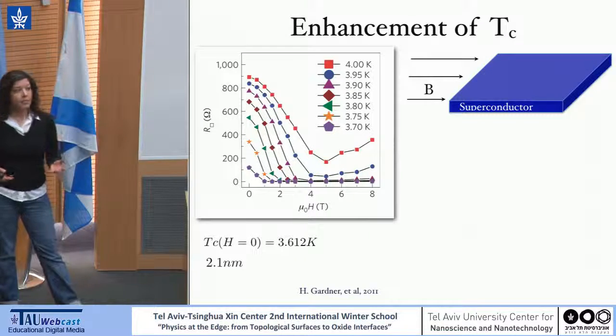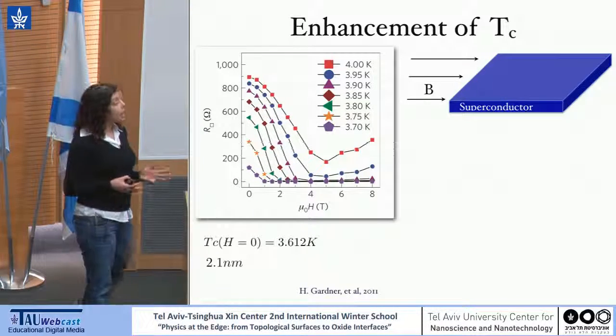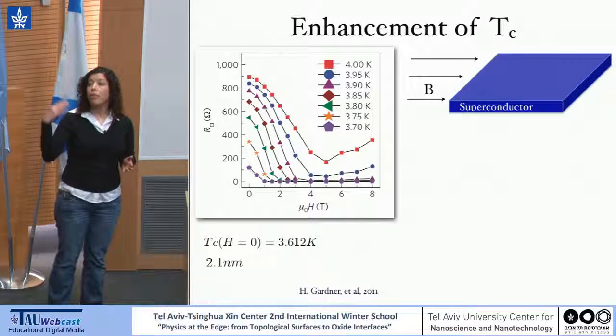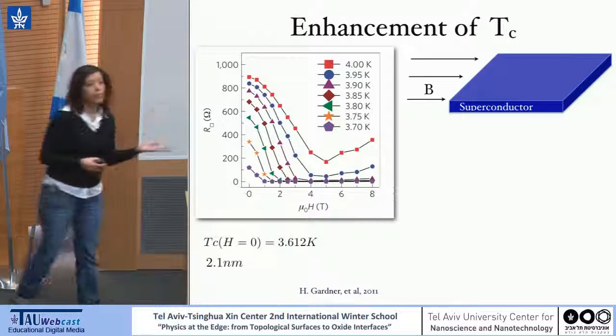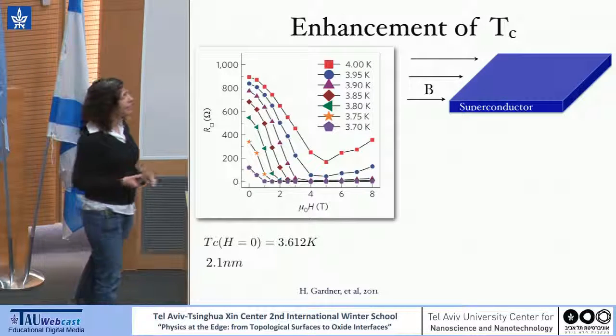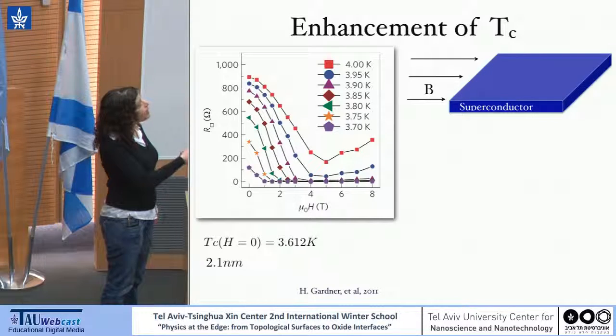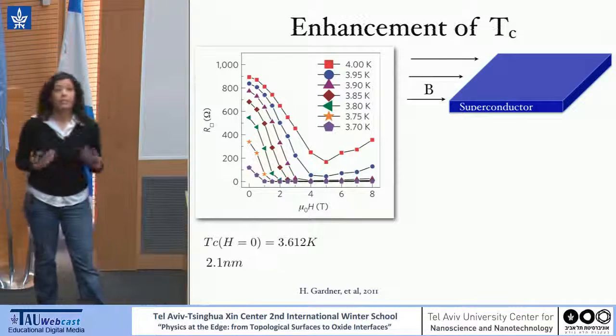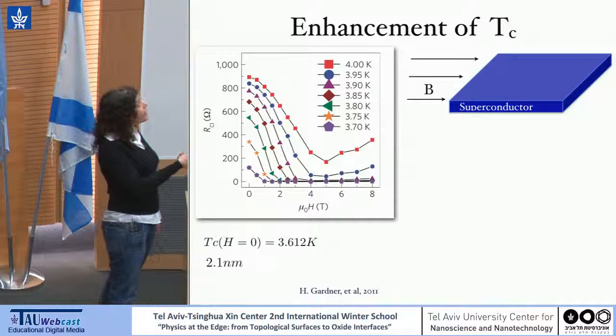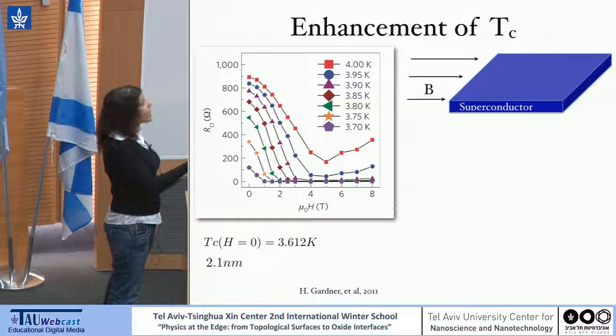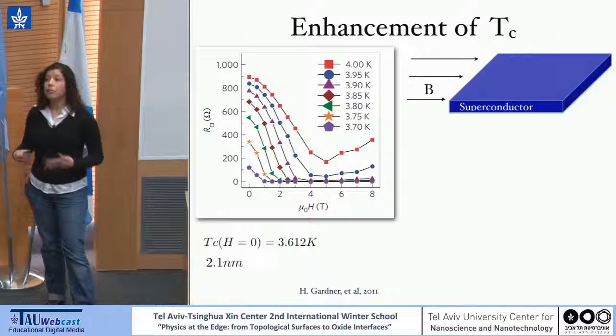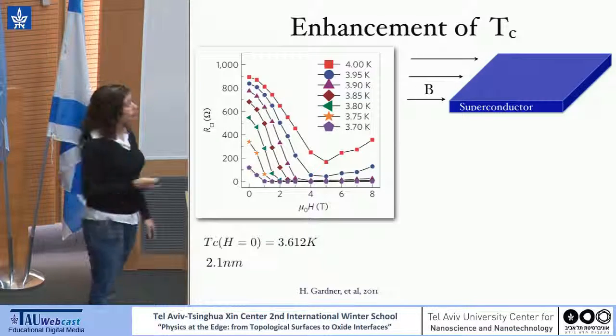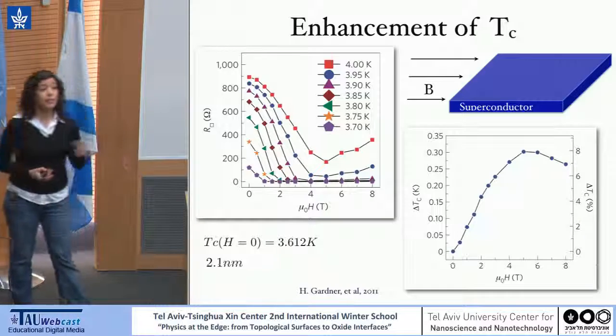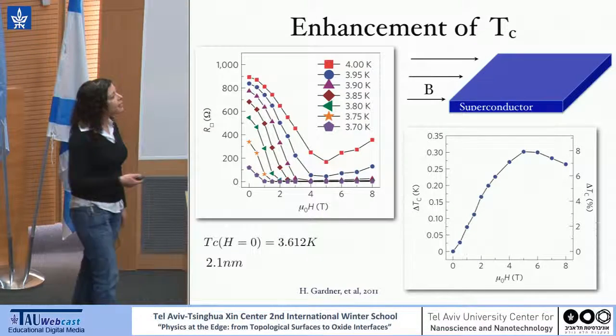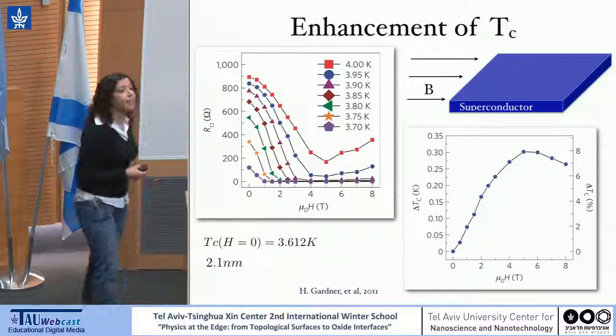Another measurement that is done on superconducting films with spin-orbit coupling was actually done both on LAO-STO system and films of lead, and they were showing exactly the same effect. So here you can see measurement of the resistance as a function of magnetic field above the critical field. And what they observe in this measurement is that as they are applying magnetic field, the resistance goes down, and actually there is a re-entrant effect back into the superconducting film. We can summarize that by looking at how Tc is changing as a function of magnetic field, and it actually grows as a function of magnetic field instead of going down.